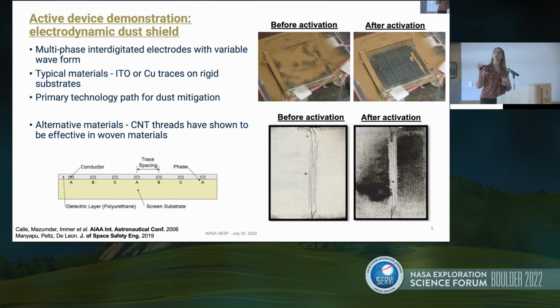So we chose an electrodynamic dust shield as the device configuration. Electrodynamic dust shields, for those of you who are not aware, I assume that's probably no one in this audience, are multi-phase interdigitated electrodes to which we apply a variable waveform to make a traveling electric wave that lifts and moves dust, or not just dust, any sort of charged particles, off of the surface. Typically, these are made with rigid materials like ITO and copper on rigid substrates.